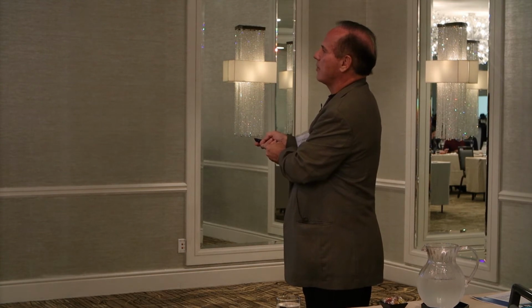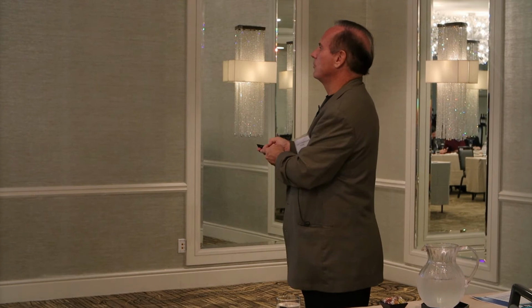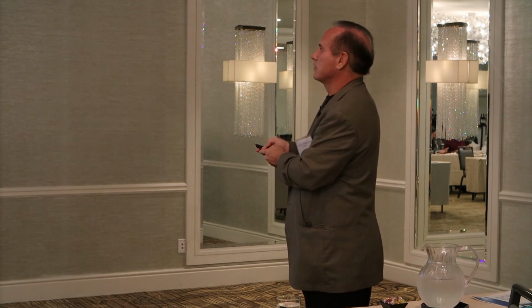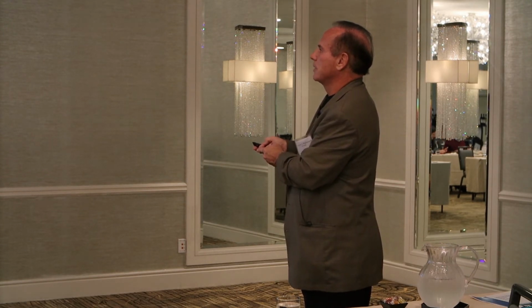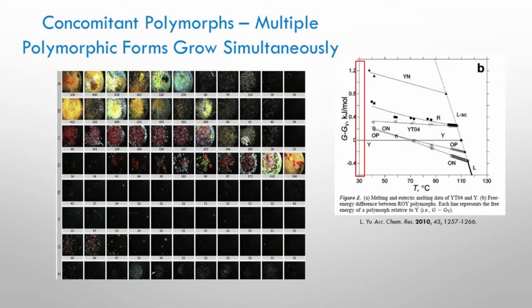And then by melting with the same miscible substance, he could measure the enthalpy of fusion and the melting point depression, and use the heat capacity changes, again at different temperatures with different amounts of that eutectic forming substance, to calculate at different temperatures the energy difference relative to the room temperature stable form.